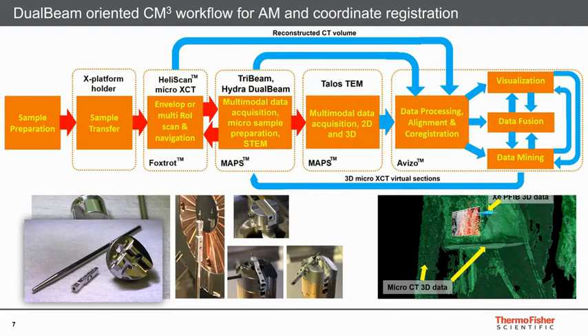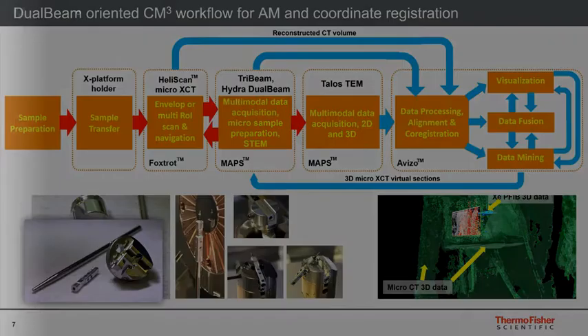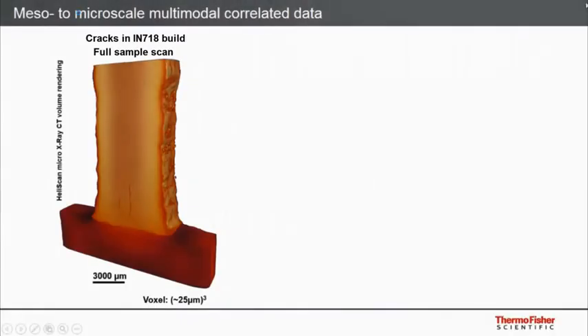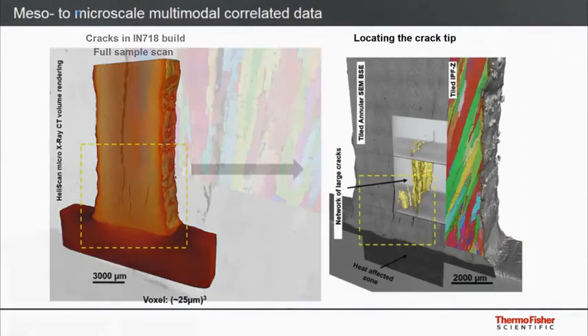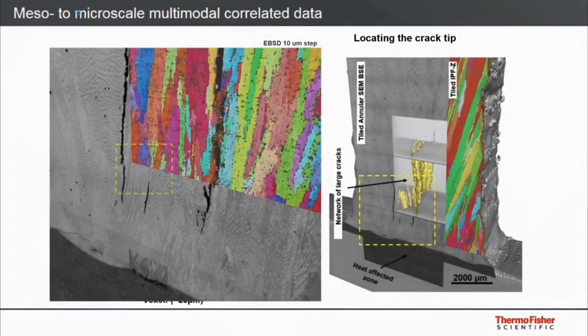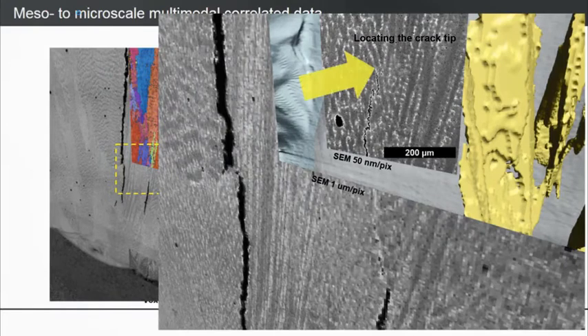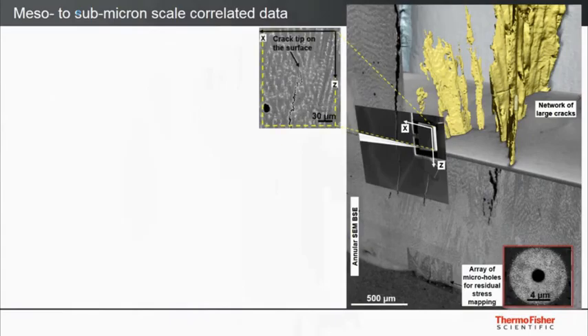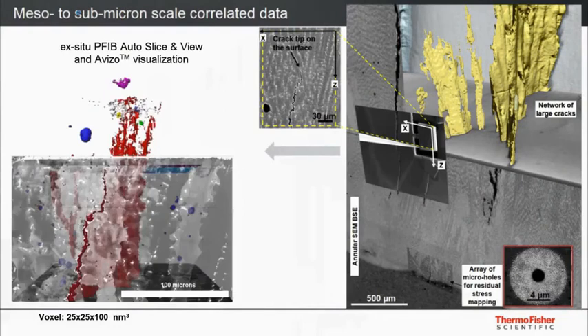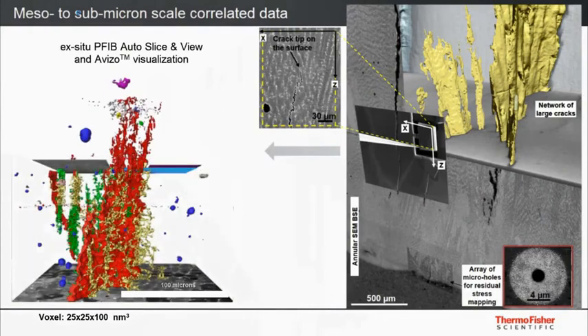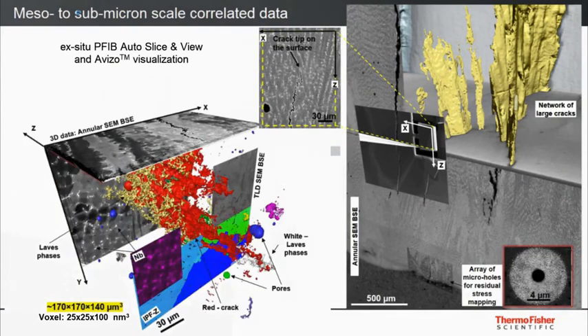Now let's have a look at the first example results of the Inconel 718. We start with a full sample scan of a component with shrinkage cracks. The correlative analysis allows us to find a crack tip. After finding a crack tip, we use PFIB to extract a small chunk for further ex situ study with a high resolution. We collected thousands of serial sections.